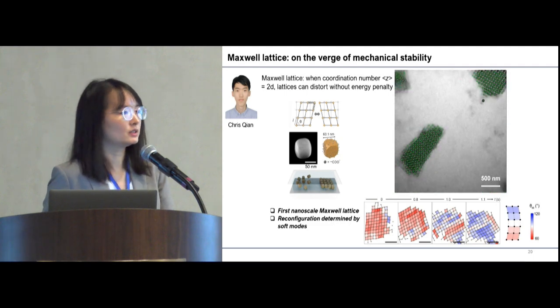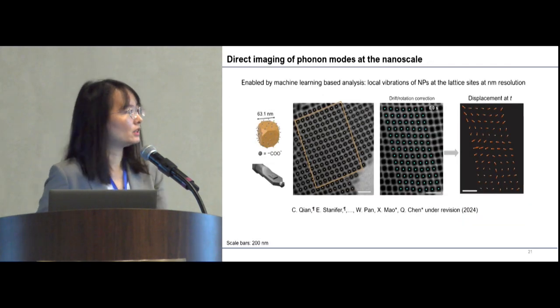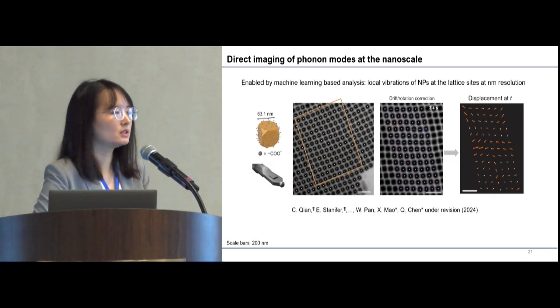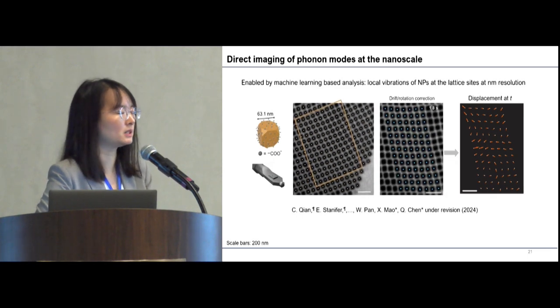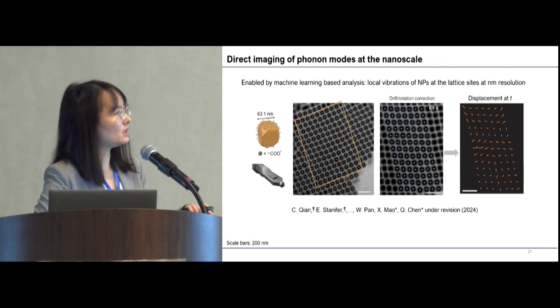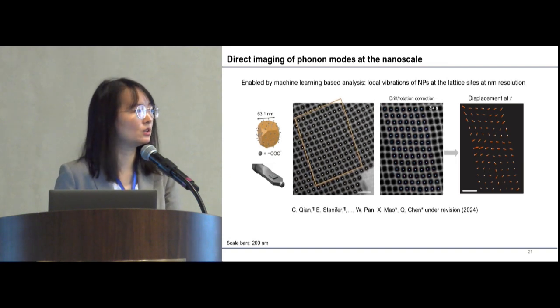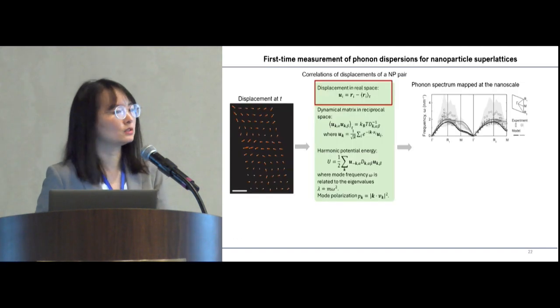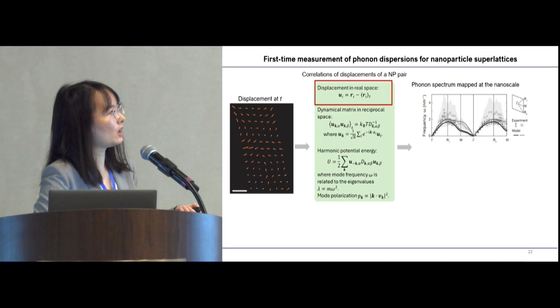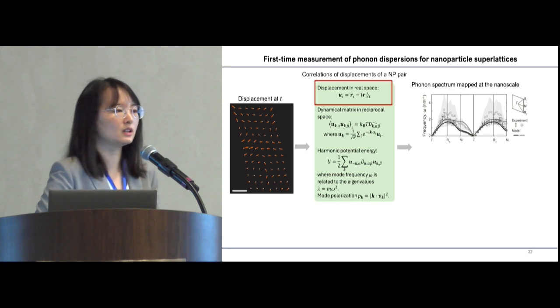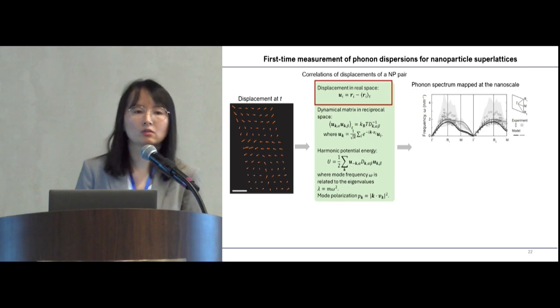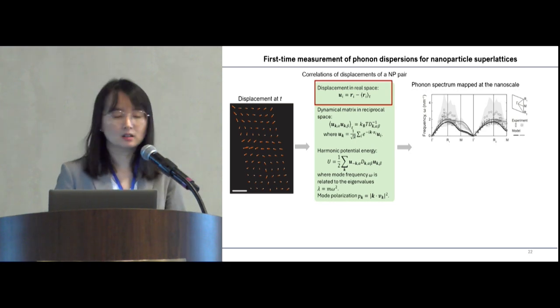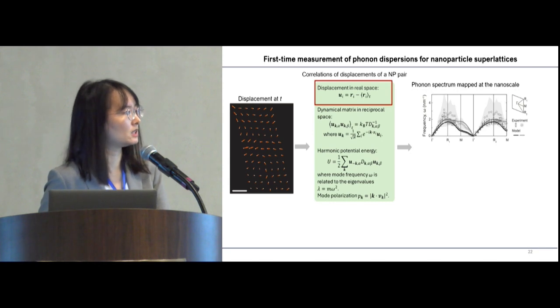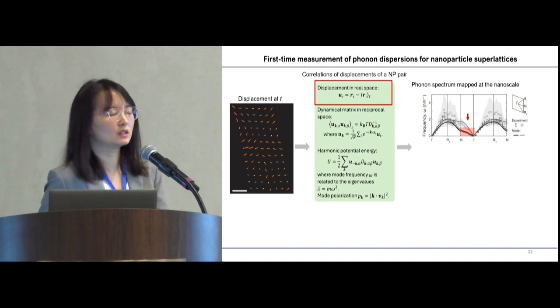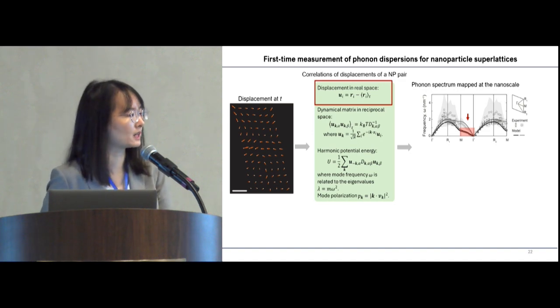So how do we measure the phonon response? As I mentioned earlier, using machine learning, we're able to accurately measure the particle position with sub-nanometer precision. So we can measure the displacement of the particles at the local lattice site. And this displacement field actually allows us to ultimately derive the phonon dispersion relationship shown here. So this is the same phonon dispersion relation as I showed you earlier, but this is the first time we're able to measure it using a nanoparticle superlattice. I'd like to highlight, for example, you can see a low energy band showing here, which corresponds to soft modes of a Maxwell lattice.